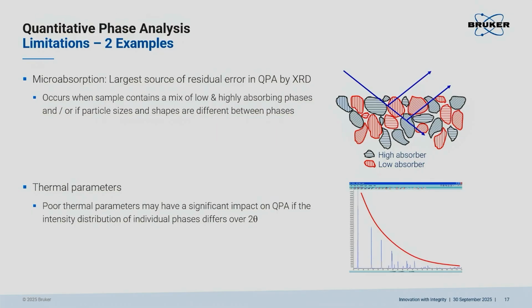Already, if you have a structure and you note, if you look at the structure data, that there are thermal parameters like exactly 0.5 or 0.7, this should raise an alarm. Why is that important? If you look at the impact of thermal parameters, you can see that this is an effect which drastically reduces intensities as a function of 2 theta, as you go to higher angles. If this value is incorrect, you will have a very strong correlation with your scale factor. And if the scale factor is off, your quant is off.